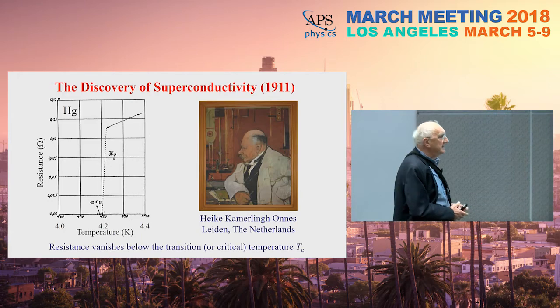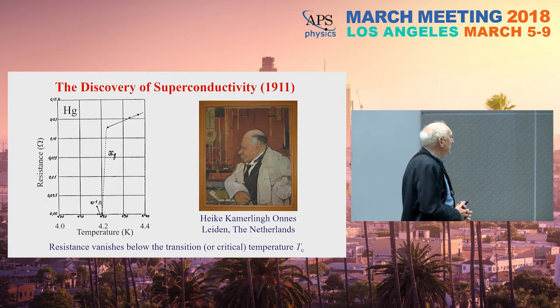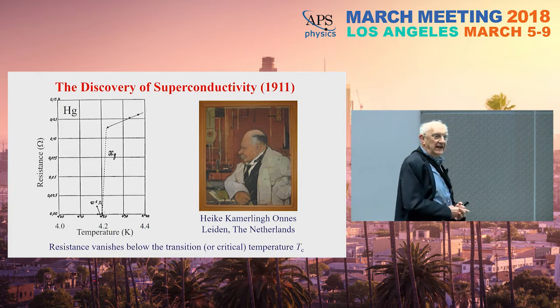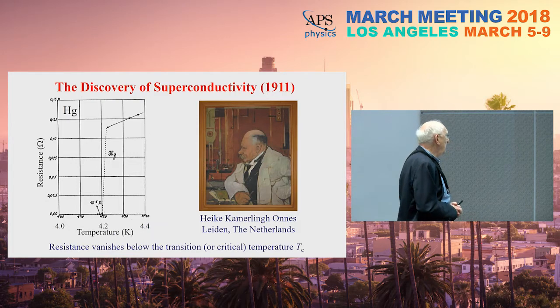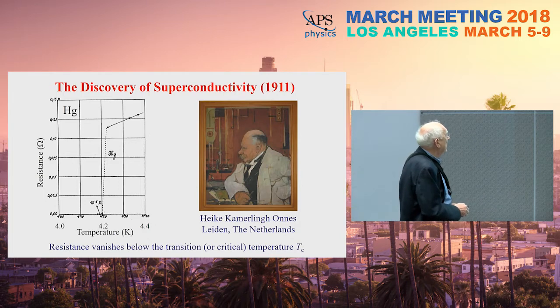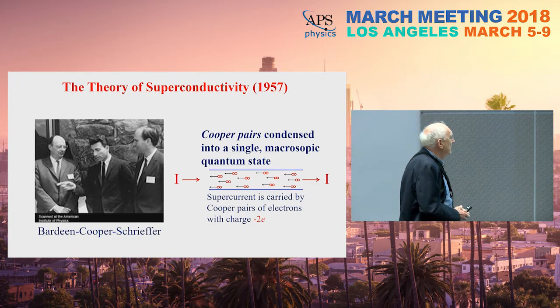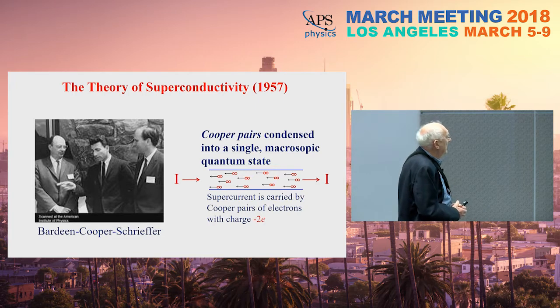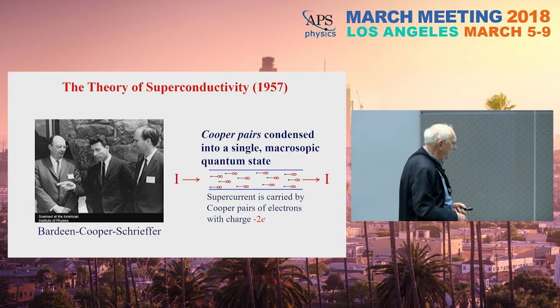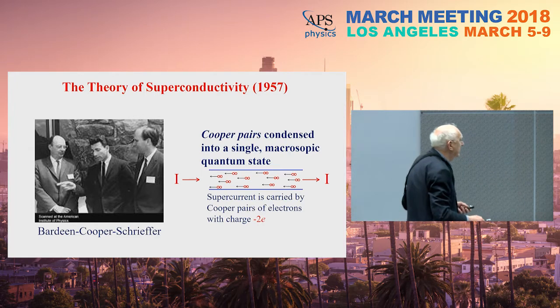The SQUID is a superconducting device, and it all started in 1911 when Kamerlingh Onnes discovered superconductivity in a thread of mercury. He cooled this down in liquid helium to its boiling point, 4.2 Kelvin, and discovered that all the electrical resistance vanished. It took almost half a century to understand the origin of superconductivity, when Bardeen, Cooper, and Schrieffer showed that superconductors are enabled by the pairing of electrons to form Cooper pairs, condensed into a single macroscopic quantum state, giving rise to supercurrent.